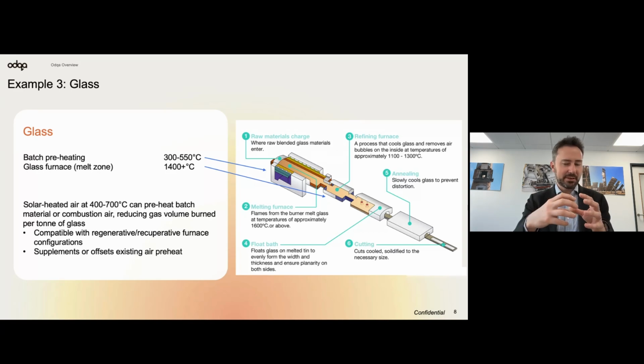So one other way to think of our technology is effectively you have waste heat that is falling on the land next to your plant. That's sunshine that's heating the ground. You can gather that heat and bring it into the preheating stage, or you could gather that heat and bring it into the furnace, depending on the size of the plant that we're building. But again, solar heated air at 400 to 700 degrees can preheat the material directly, or we can bring it into the furnace to directly reduce the volume of gas that's being burnt for the glass industry,